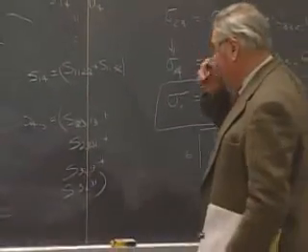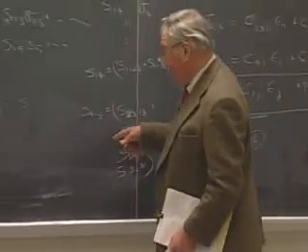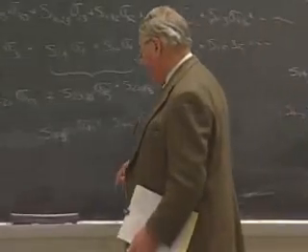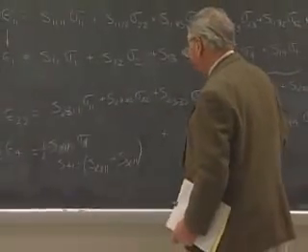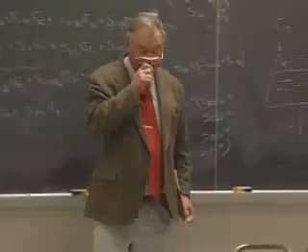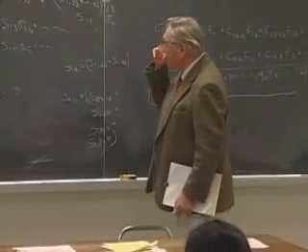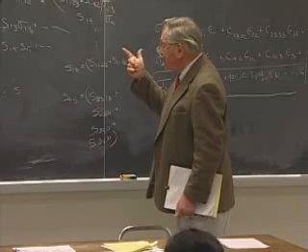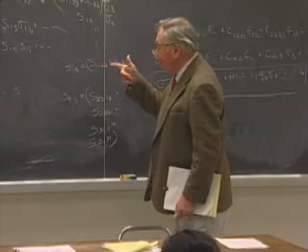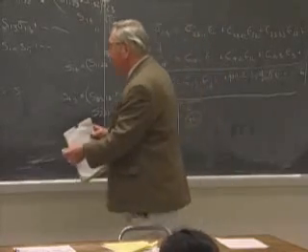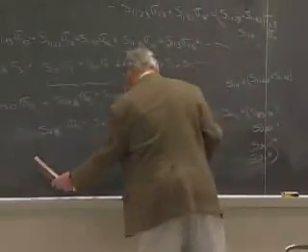So we're going to have to put in a factor of 1/4 in front of the S45 in order to accommodate 4 of those terms. So our definition then in going from tensor compliances to matrix compliances is much more complicated.